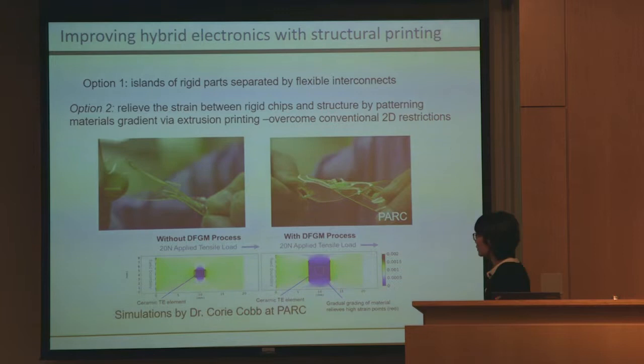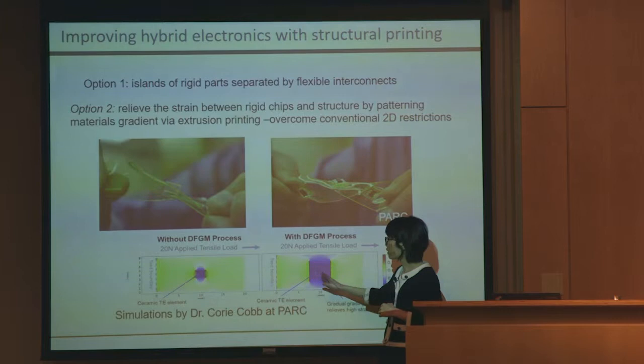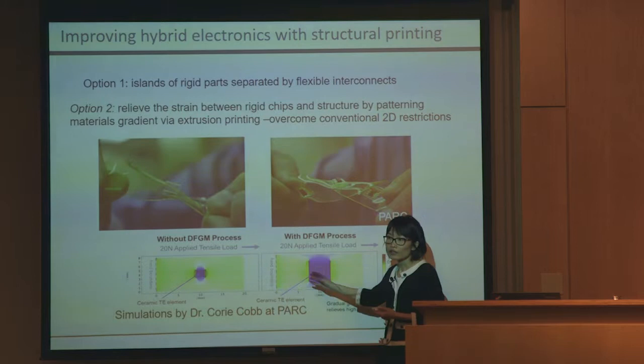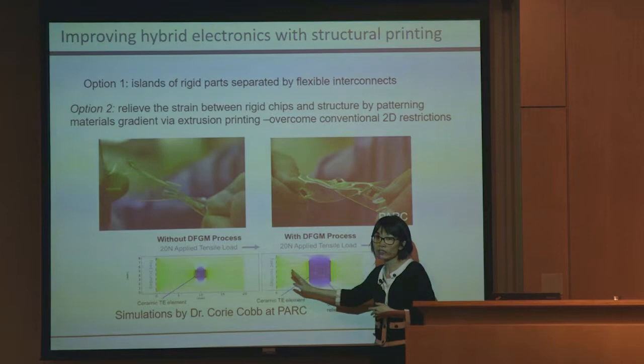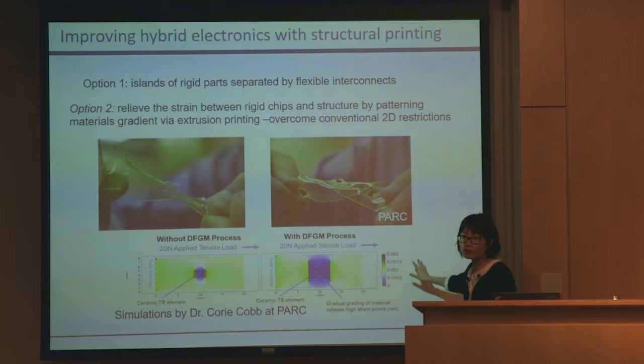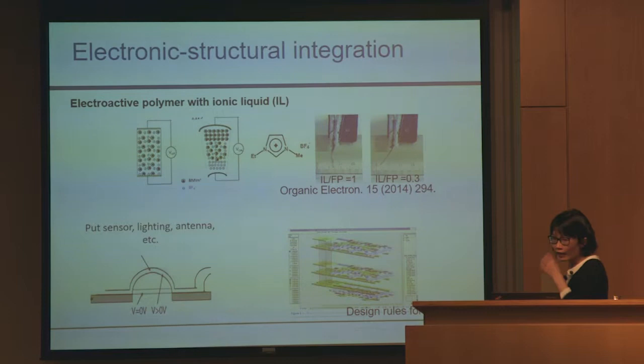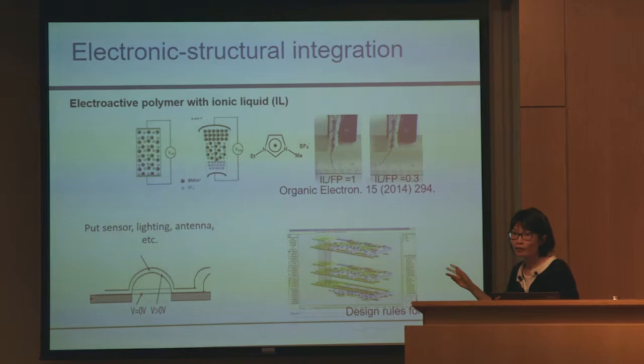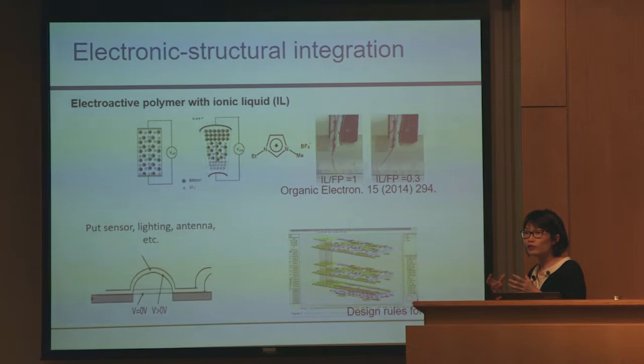So with a mechanical engineer, we decided that instead of an abrupt interface, we just need a gradual transition. With materials, we can tune the cross-linker ratio from the rigid surface to the flexible substrate, and now we have a gradient. That could relieve the stress, and then we can have rigid chips on flexible substrate very reliably. That also inspired us to do work on electroactive polymers. What this means is I also want to build structures that can be actuated electronically.